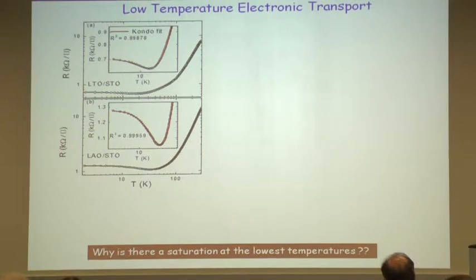Now I want to talk about the electrical transport in this system, which is also quite exciting. And I will show you two plots here. The resistivity of the LTO-STO system. You start cooling down, it's a perfect metal, and then you see a minimum, and then it starts saturating. If I blow up this section, this is what you have.